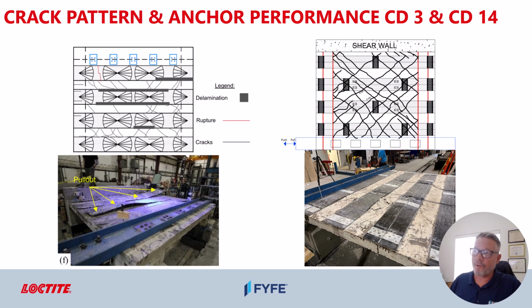You can see again the photo of the specimen on the left, CD3, with the traditional FRP anchors where the anchors have pulled out. Notice on the right, this is post-peak on this specimen, where none of the anchor plates have pulled out, none of the anchors have failed. They're all able to hold on, transfer that load from the laminates very, very effectively and efficiently, and achieve not only higher peak strains, but higher peak performance, higher peak ultimate loads, and a better crack pattern.